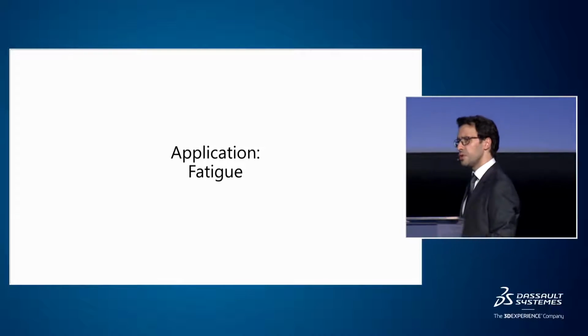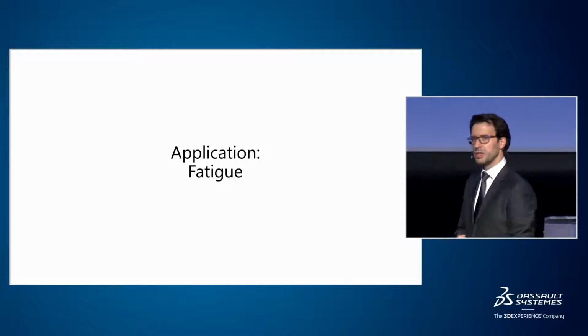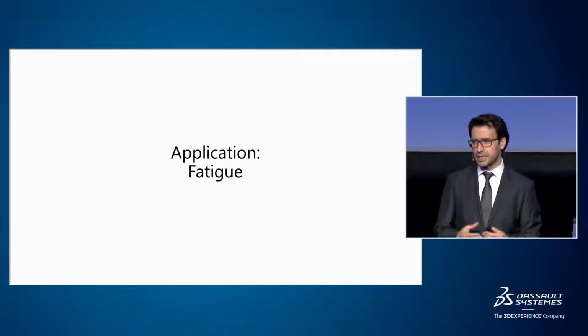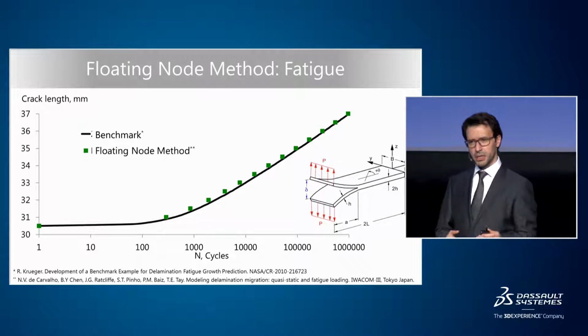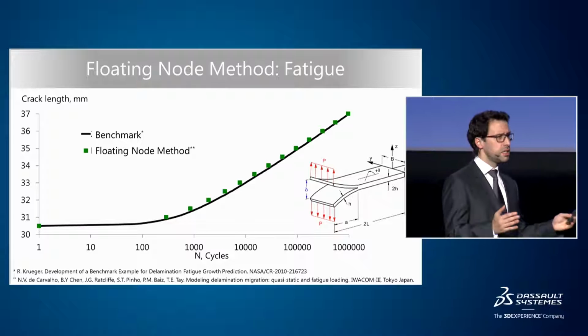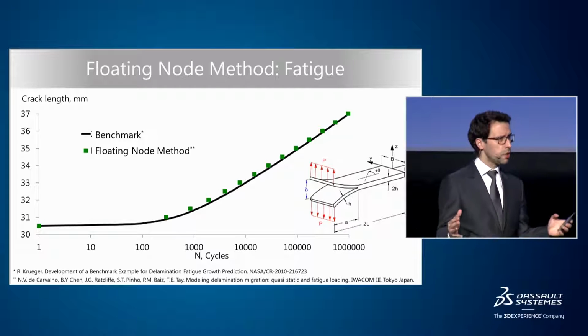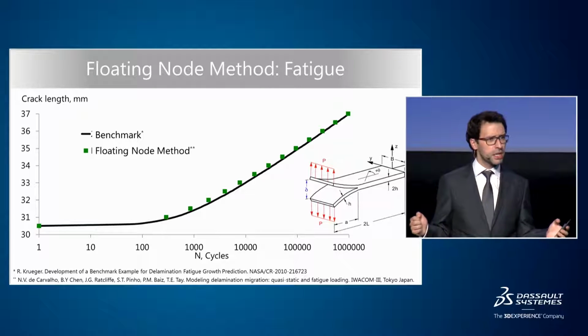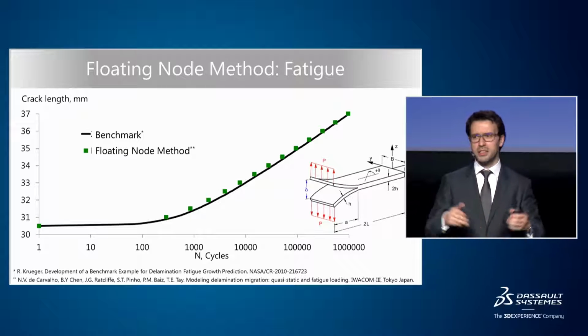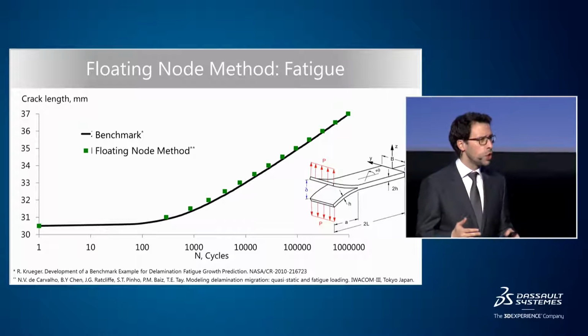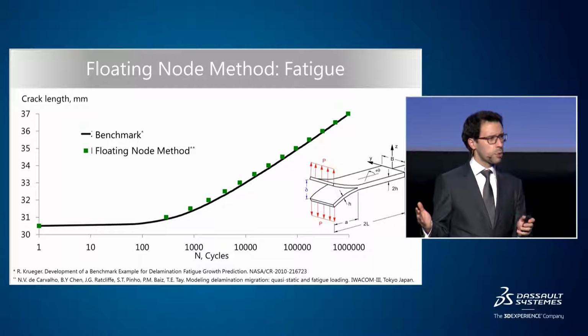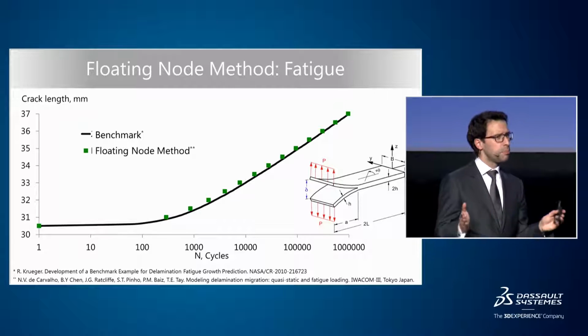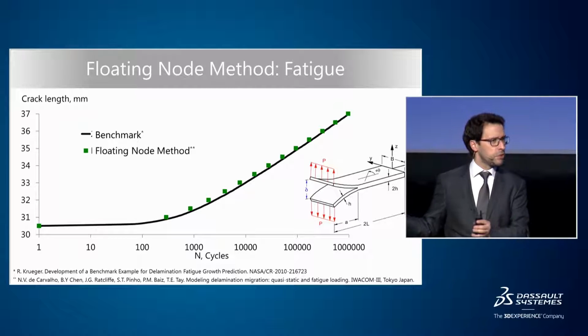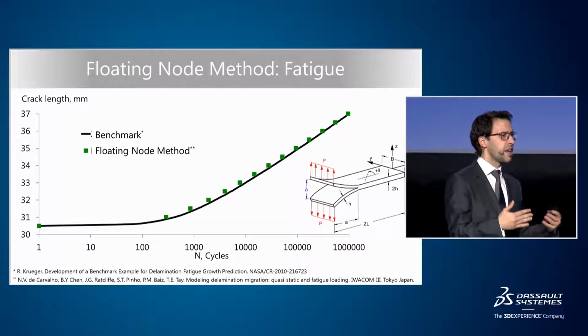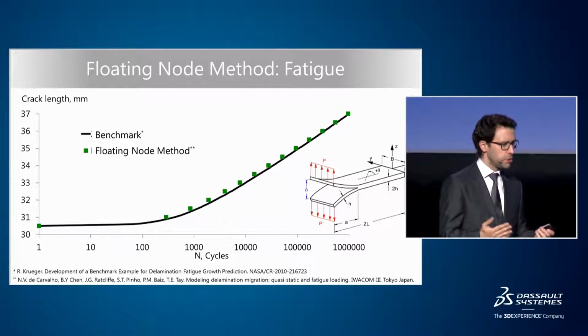Now I'm going to show you an application or an extension that Nelson at NASA did for fatigue loading. This is a DCB specimen loaded in fatigue. So fatigue is something that I would assume most of you are familiar with. In case someone is not familiar with it, if you load a certain piece of material until a load that should not lead to crack propagation, but you do it repetitively for thousands of cycles, then cracks can still grow in this way, which we call fatigue.